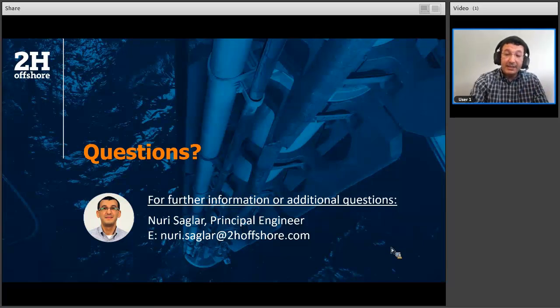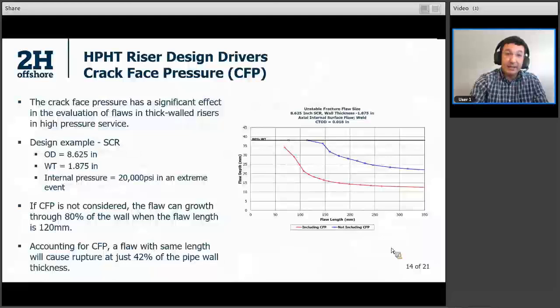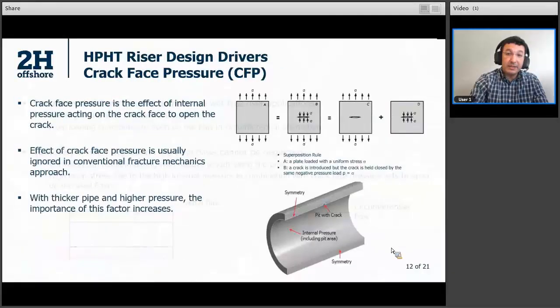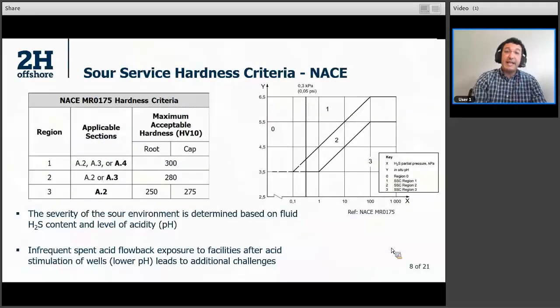But when we look at that one, as I stated before, let me go back to that slide again. Okay, this NACE requirement. Basically, NACE is saying that if you are in the severe sour region, region 3, your hardness requirement shall be less than 250. And to weld the thick pipe wall and try to stay below 250 is a challenge. Maybe that is the most challenging part of this system, because it is difficult to weld and achieve this target hardness value. It requires very good quality welding and very good quality welders, and it will impact your speed for the fabrication and installation. So this is maybe the most challenging area if we are talking about the welded wet-3 riser systems.